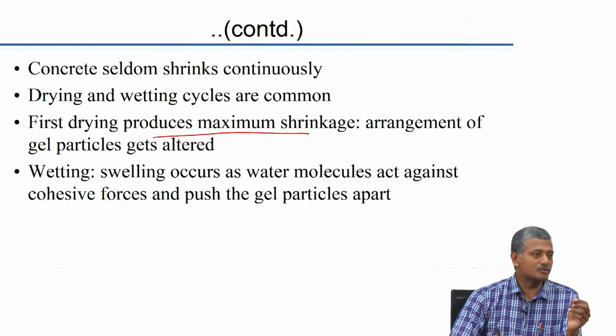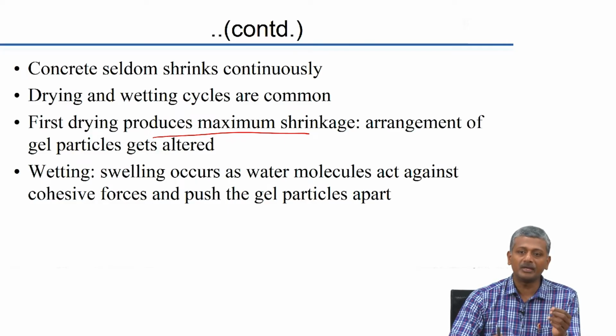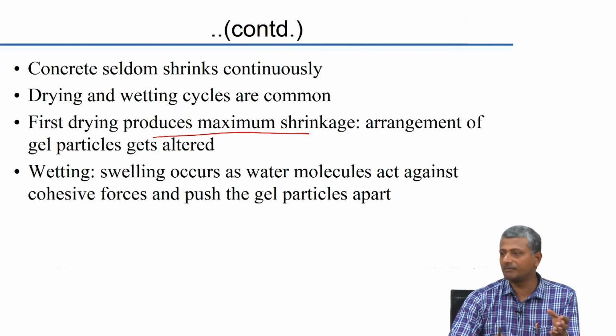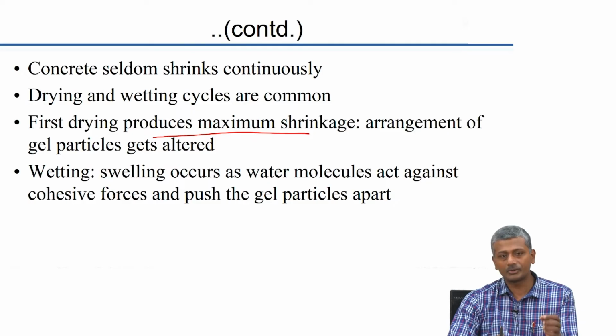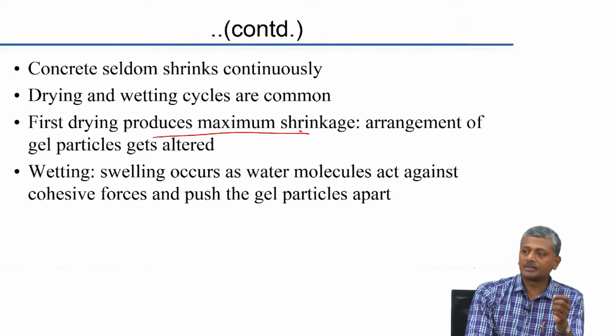But because of the size of the pores, there are only some pores which can be filled again with water. So, rewetting can only fill up certain pores. That is why the swelling amount is not equal to the first shrinkage amount. There is always some permanent shrinkage that is built up in the system.